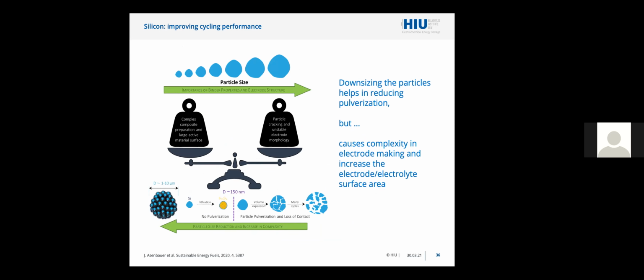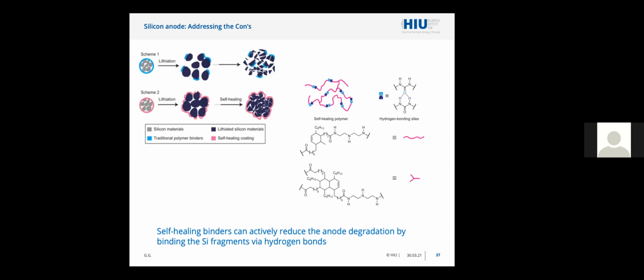So it is always a balance in the way we can solve the pulverization problem of silicon, associated to the large volume change. Okay, there have been many approaches proposed. One of these is, for example, using binders that can self-heal. Actually, this is also one of the important subjects in Battery 2030+, right? Self-healing batteries. These polymers have the ability to bind on the silicon particles even after pulverization, and keep them together, preventing at least the mechanical degradation.